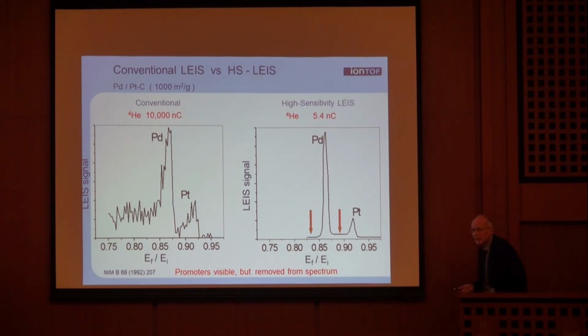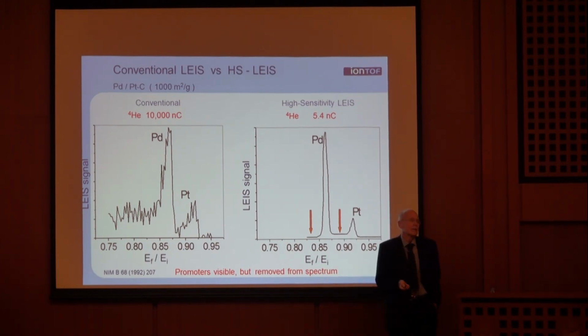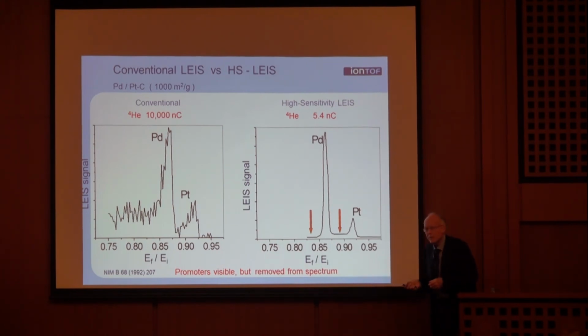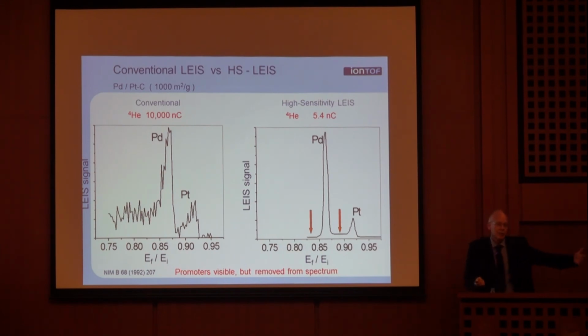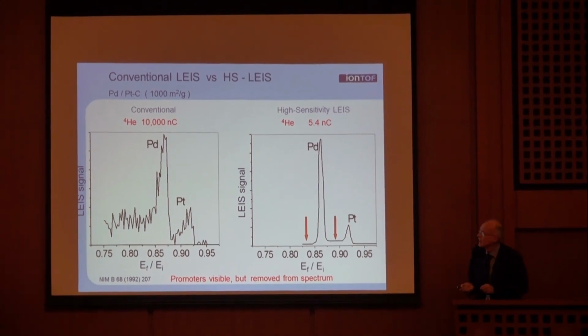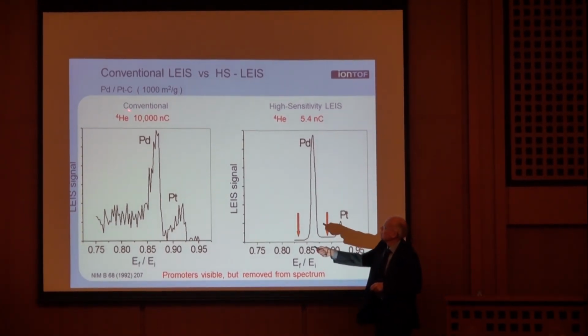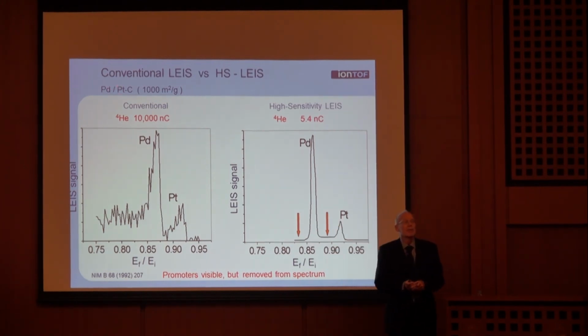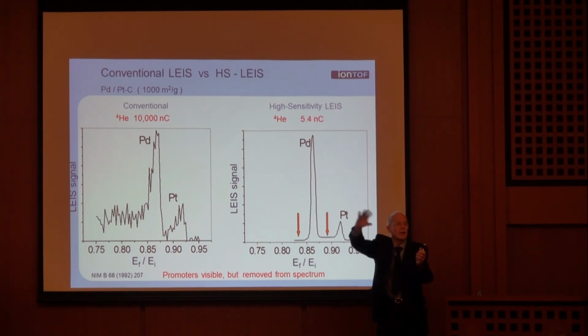This is the spectrum that many years ago really got us going. We had been doing ion scattering for a long time, and I'm also a little bit professor of catalysis, so we would look at real catalysts. We started off by looking at palladium, platinum nanoclusters on a carbon support. And carbon is very, very rough, so it's difficult to measure. If you would do that with a technique like XPS, there was so little on it you don't see anything. You only see carbon.